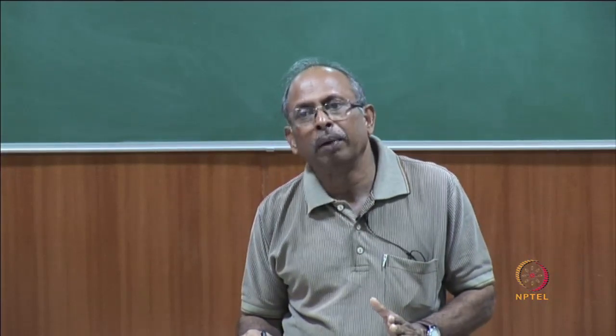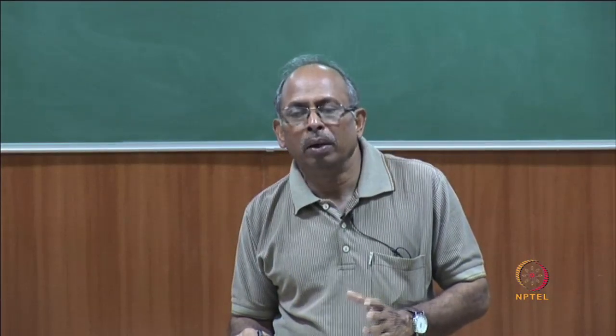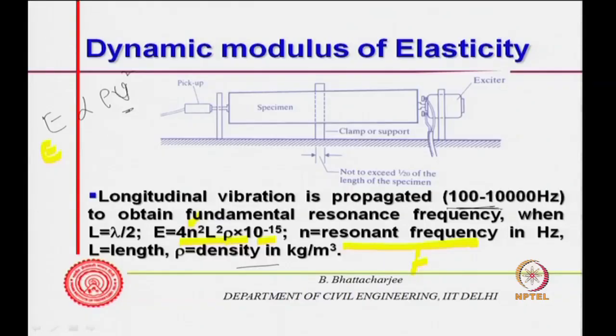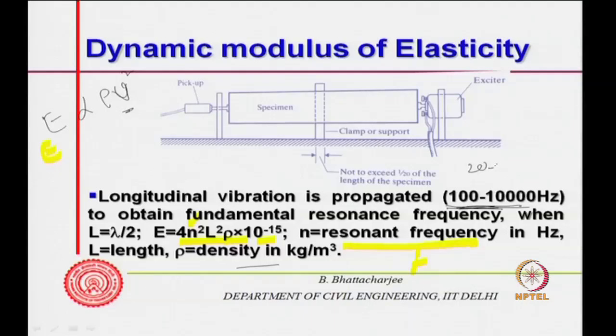To begin with, what you do is impart longitudinal vibration or mechanical waves, so excite through acoustic waves from 100 to 10,000 hertz. It is actually sound, because sound is from 20 to 20 kilohertz. So, it is not ultrasonic; this is actually sonic excitation you provide, and then find out from this the modulus of